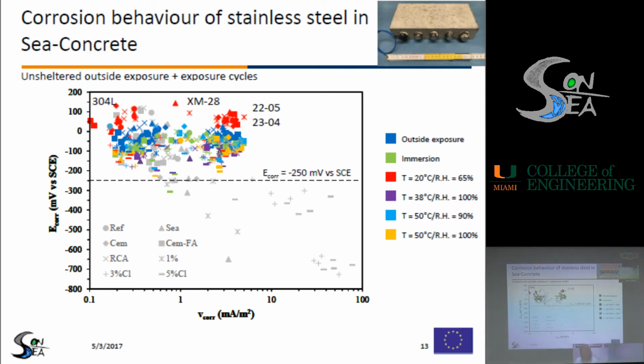humidity. Comparable results were obtained on the duplex stainless steel 2205 and 2304, indicating that even on this stainless steel bar, no corrosion occurred when they were embedded in the concrete with the highest chloride content and exposed to the harshest environment. On the XM28, which is the less alloyed stainless steel, corrosion did not occur in any of the exposure conditions. So these results show that the stainless steel employed in this study are suitable to be used in concrete contaminated by chloride when no further penetration of chloride is expected.